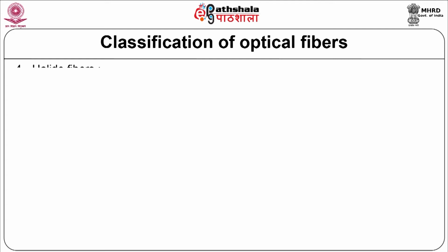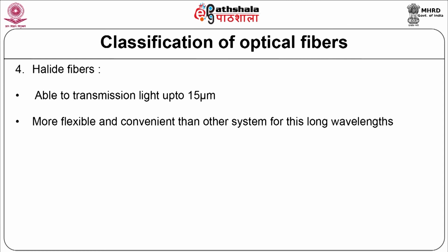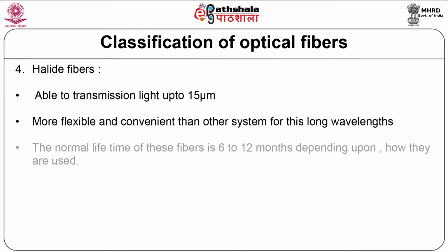Next type is halide fibers, able to transmit the light up to 15 micrometer. They are flexible and convenient than other systems for the long wavelengths. The normal lifetime of these fiber is 6 to 12 months depending upon how they are used.